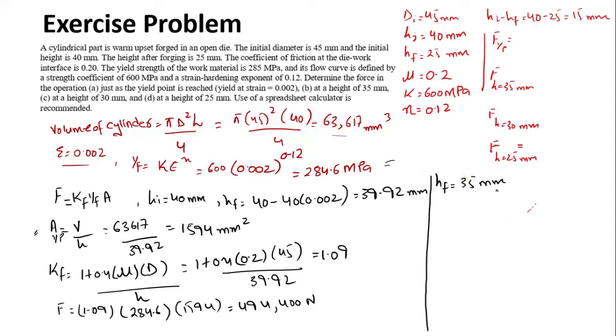And we have the strain value. The strain value would be equal to ln of 40 by 35. So we have strain equal to 0.1335. This is the value of the strain.